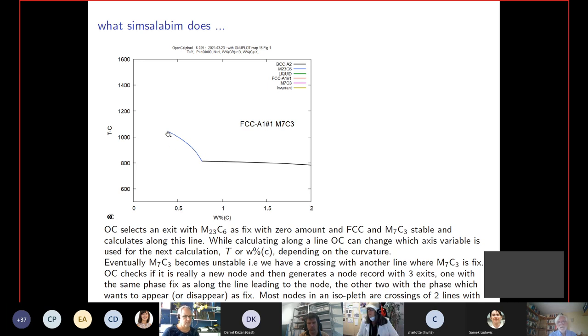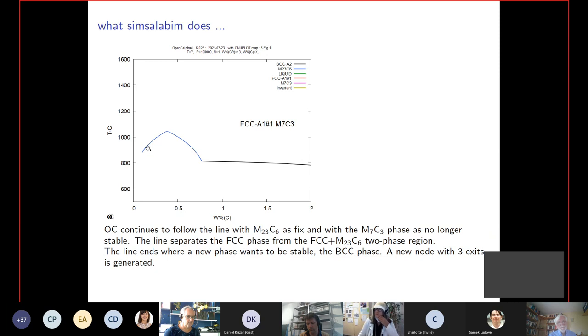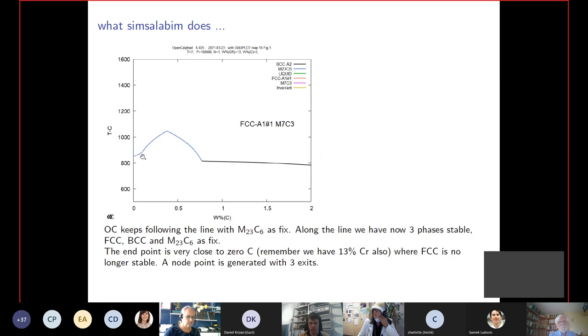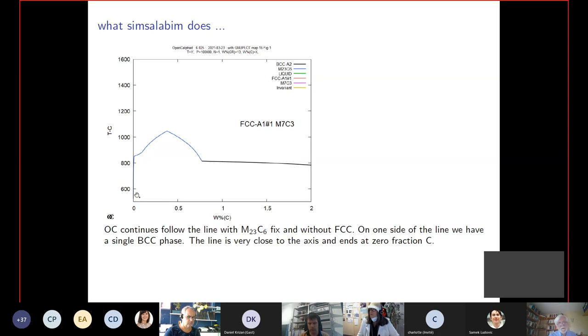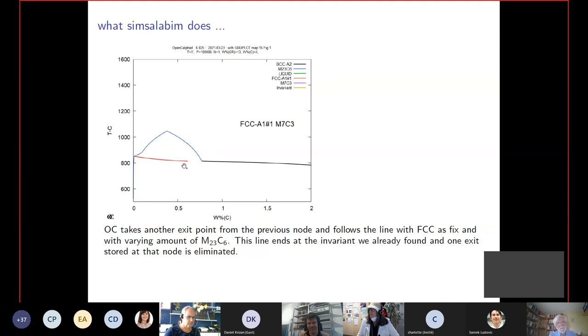So it calculates a line here, and here it finds another node point where actually the M7 carbide is no longer stable. And then it continues to follow a line where the M23 carbide has zero amounts. And then it will follow where you have, here, it finds BCC phase. So it finds a three phase equilibrium and goes on this line. And this doesn't show up very well, but here it follows where the M23 carbide disappears. And then it will follow where the FCC phase is no longer stable. And here it will end at the invariant that we already found at this point.